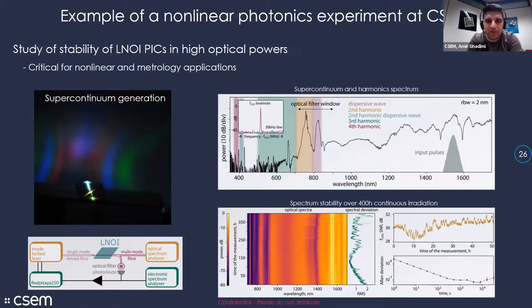I don't know specifically what sort of effect you have in mind, but one of the first things that was concerning for us was the crystal damage at high optical irradiation, and for reasons which we don't yet understand, this seems to be absent in thin film. People have reported it in bulk, but we don't see it, and we still don't know why. Phenomenologically, we just don't see it.